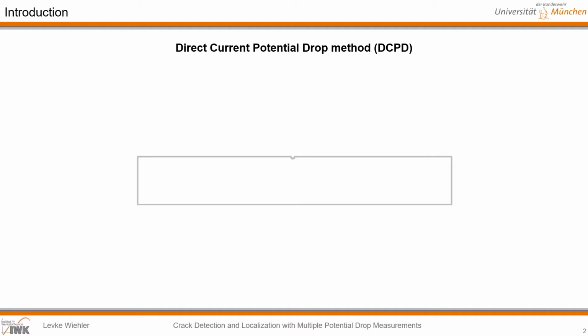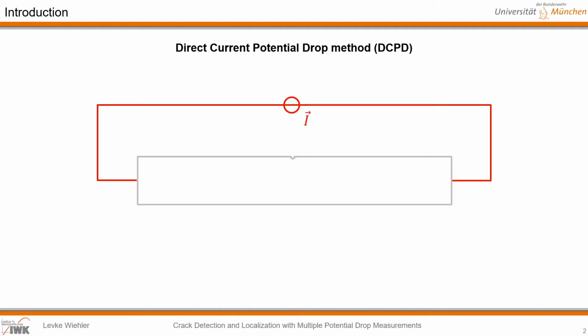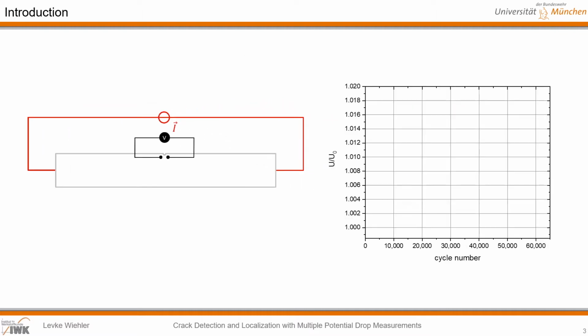Let me start off with the introduction into the direct current potential drop method, short DCPD, which is commonly used to measure the crack length in fatigue tests. Therefore, a DC source conducted a time-stable current through the specimen during the test. The measured voltage U represents the difference between two potentials. On the right side, the relative potential difference is plotted over the cycle number.